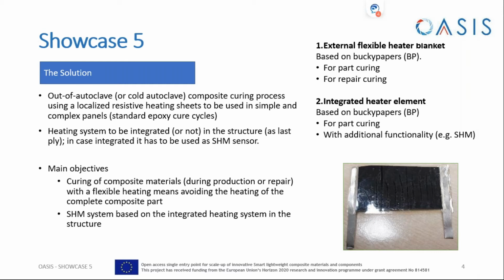In the showcase, we are focused on two different solutions: the external heating system, in which case we will use a heater, apply the cure cycle and then remove it. And the other possibility is to use an integrated heater element. In this case, the heater element will be placed on the part, will be used to cure the part, and will stay on the aircraft during the in-service life.